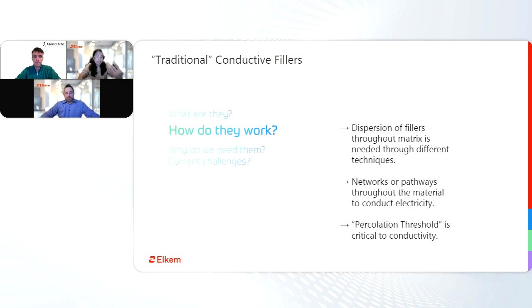How do they work? These fillers are dispersed throughout the matrix using a variety of techniques, respective to what the filler matrix is chosen. Once the filler is dispersed and cured in the network, it creates pathways of these fillers to form so that it can conduct electricity throughout the material. There's a critical amount that is needed to be reached for each type of filler and the matrix to allow that conductivity to begin. This critical point needed to be reached is called the percolation threshold.